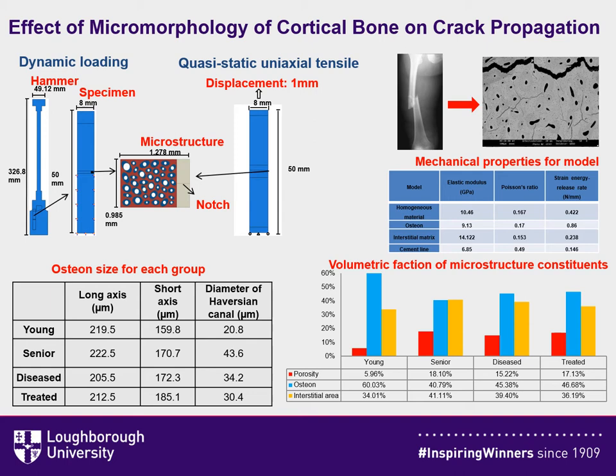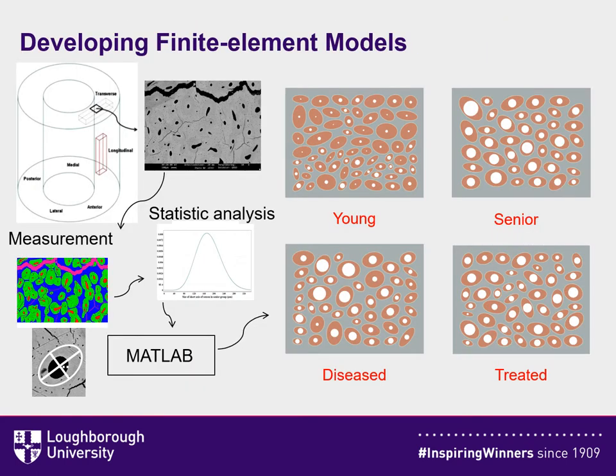This is reflected also in the properties of the osteons in each of the groups. In order to incorporate these features into the models, instead of the direct reproduction of the scanned images, we rather preferred to do the statistical analysis, looking at different types of statistics for different constituents. And as a result, we introduced four types of the representative volume elements for each of these four groups. This provided us with the opportunity to have different statistical realizations for the same set of parameters inside each group. You can immediately see some differences, most pronounced for the young as compared to the senior groups.